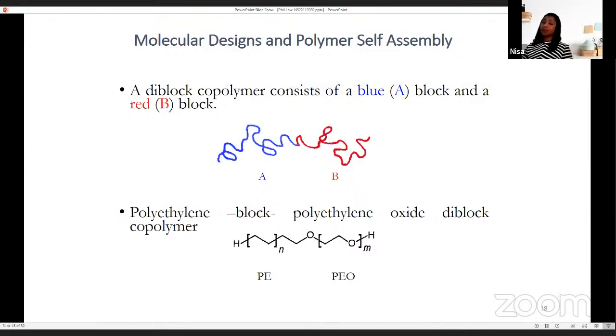To create structures or designs at nano levels, we use a class of polymers called block polymers. These are polymers that consist of two or more polymers bonded together by a covalent bond. Here is a representation of a block polymer, where the polymer has two units joined together, called a diblock polymer. Because these polymers possess a covalent bond, the blocks cannot be separated or mixed together. But these block polymers can undergo a phase separation process, and that's the way they make structures